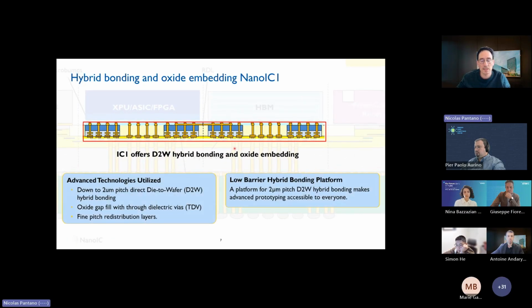So what is inside that PDK? Well, as soon as the pilot line is launched, you will be able to do prototyping down to 2 micron pitch die-to-wafer hybrid bonding with an oxide field and with what we call TDVs, through dielectric vias. In that sense, you have a connection from both sides, but also pass-through. So you would have TSV through your active die or your bridge, and also a direct connection from both sides. This is part of the NanoIC.